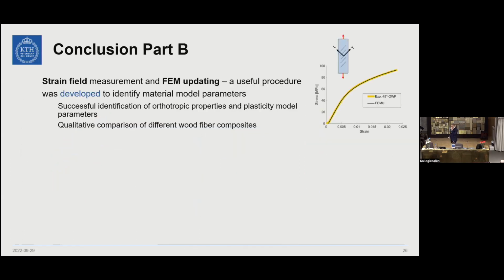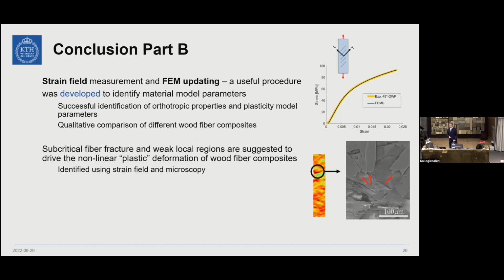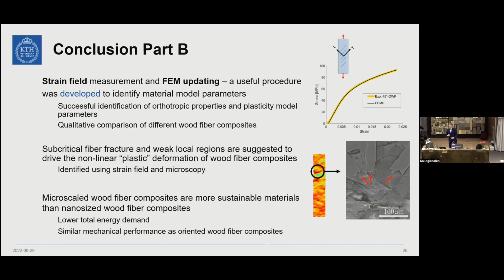So we have seen that we can use this finite element updating procedure to identify the properties, both nonlinear and linear, for nonlinear material behavior. We can see that using strain field measurements together with microscopy, we can identify the reason for these localized weak regions in the strain field. And using microscaled wood fiber composites is more sustainable than nano-sized wood fiber composites.